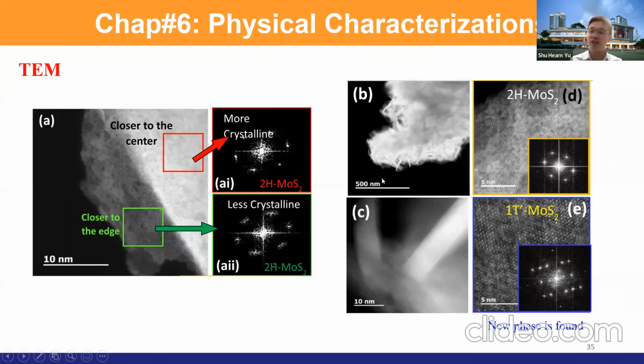And more importantly, we did TEM, and we find that during the controlled surface sulfurization, a new phase forms. This is 1T prime MoS2. If you perform full sulfurization, you can only get MoS2 and nickel sulfide.